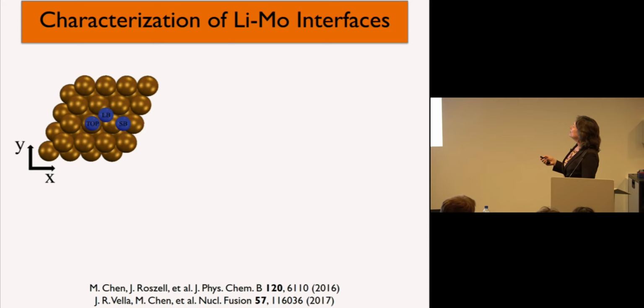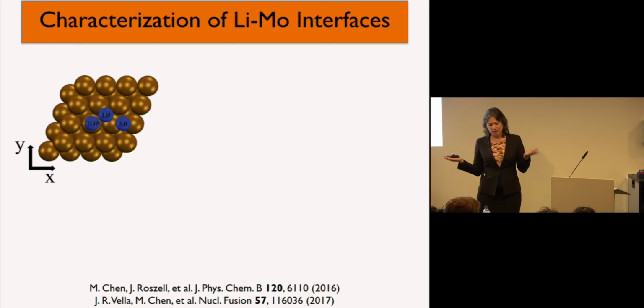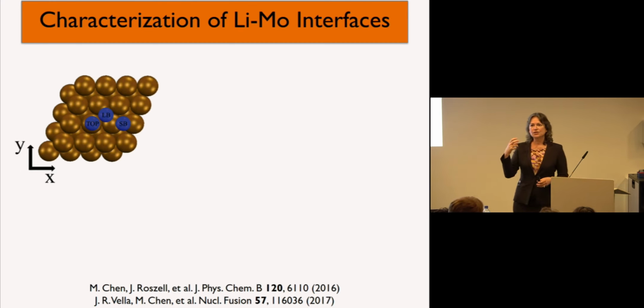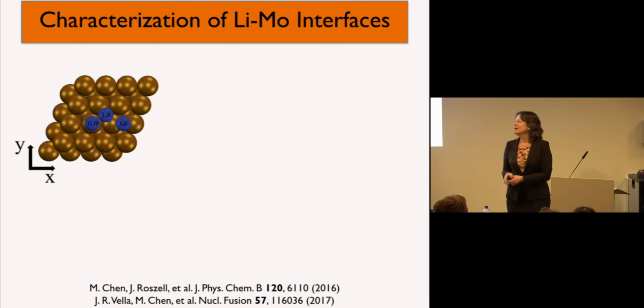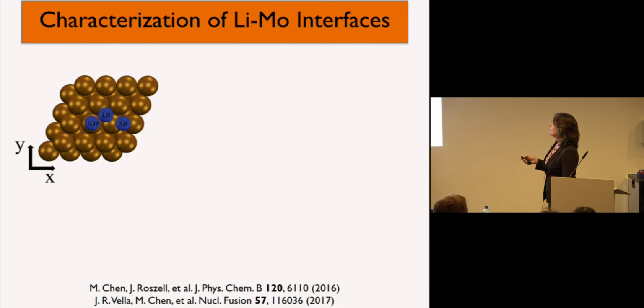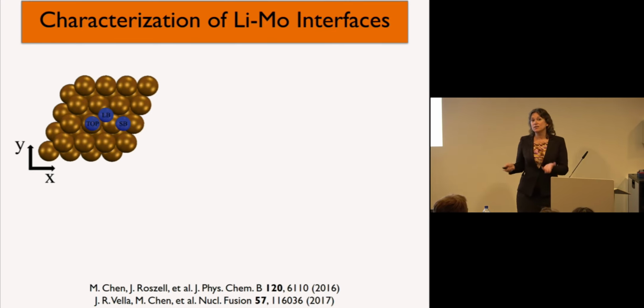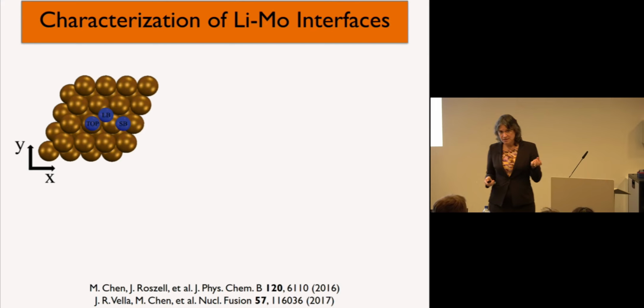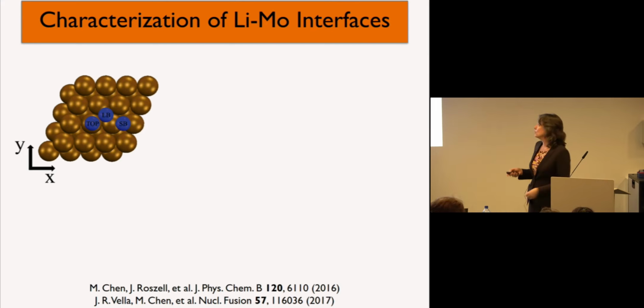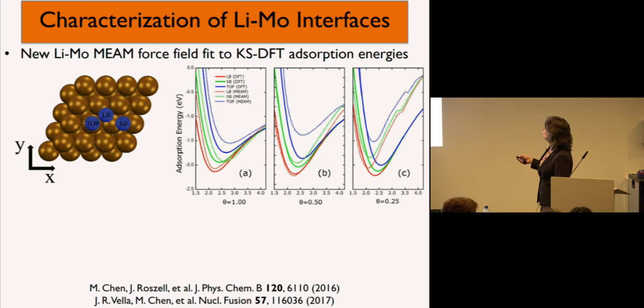So anyway, the other thing we were interested in is, it turns out that the substrates they're using are looking at molybdenum as a possible substrate on the wall for lithium to be kept in essentially little cavities, and so there was an interest in understanding the interactions of lithium with molybdenum. And again, this is a case where we have to use Kohn-Sham density functional theory, because we don't have a good description of molybdenum in orbital-free DFT. So we did a lot of work just mapping out Kohn-Sham DFT interactions of lithium with a molybdenum substrate.